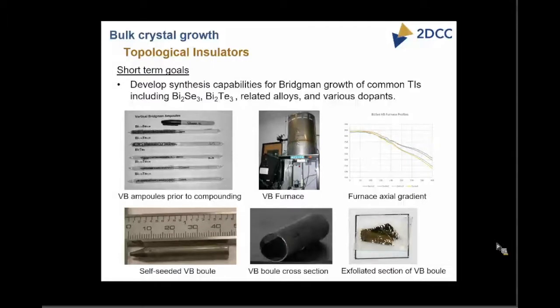This slide shows, again, from the seeding perspective, a cross-section where we've got essentially a single grain material. This is about a 5 millimeter diameter boule with a small secondary grain. And then from that, we've exfoliated sections of the boule. We are now in the process of taking this material and starting to look at electrical characterization of that.